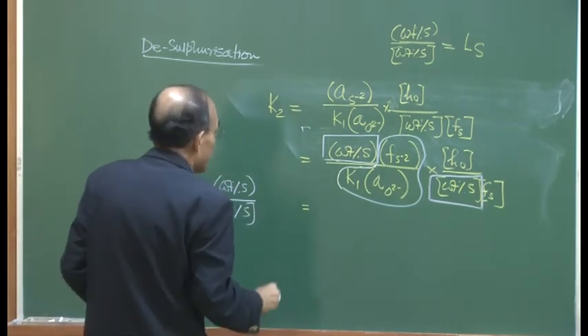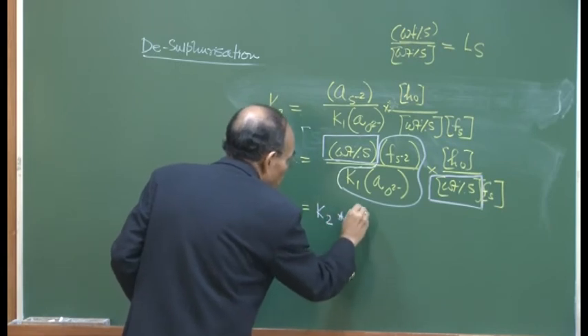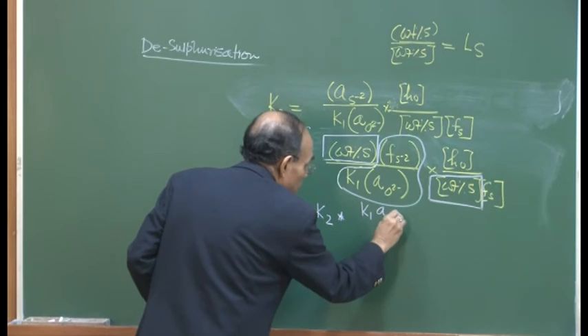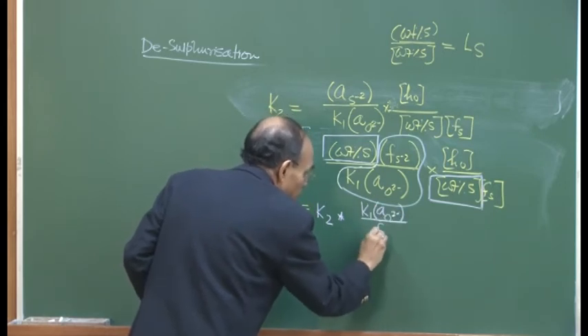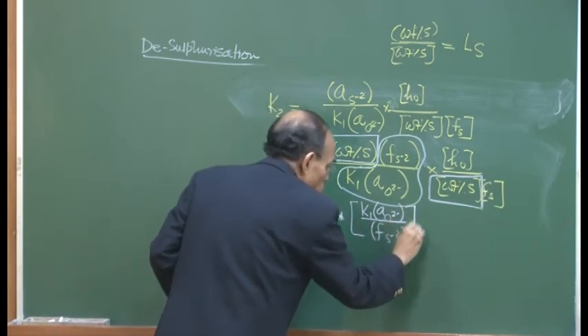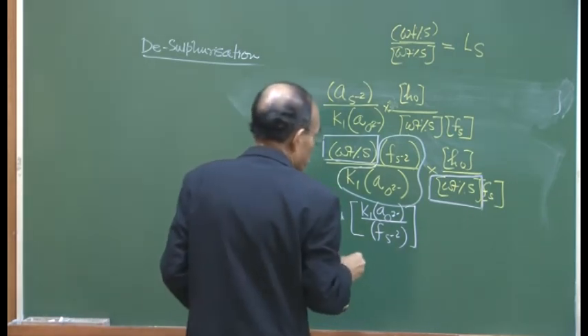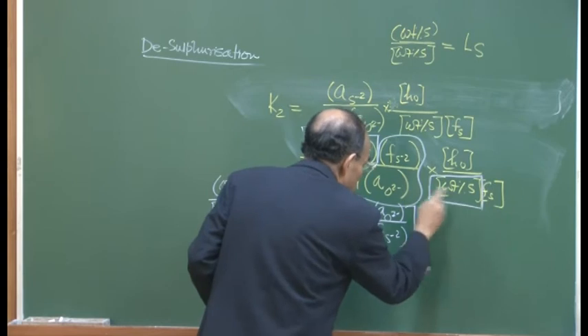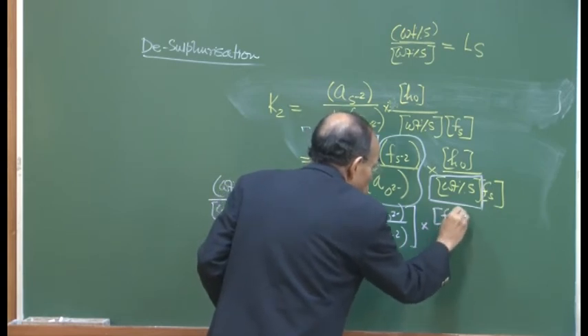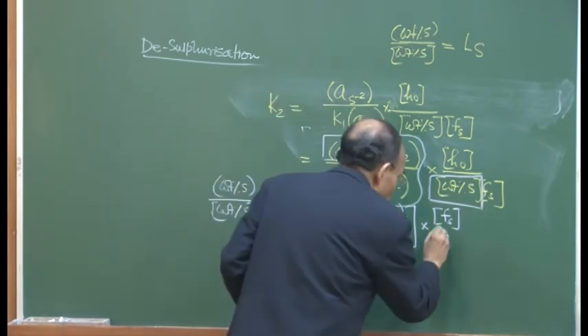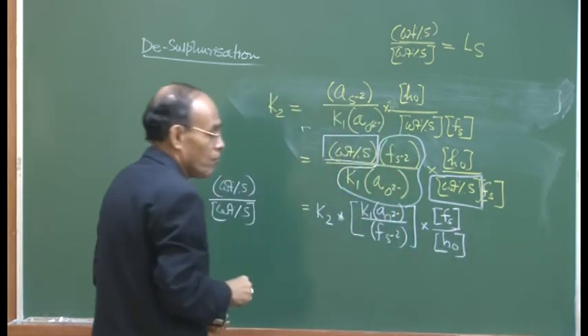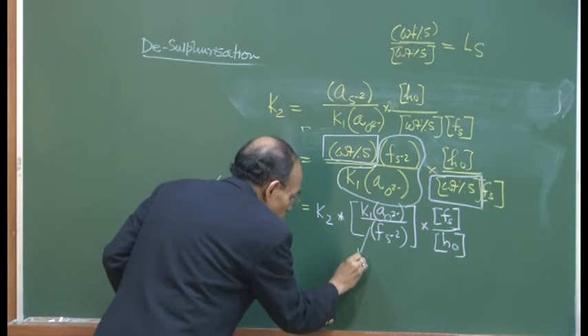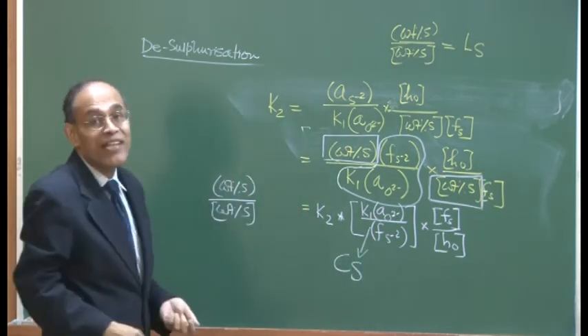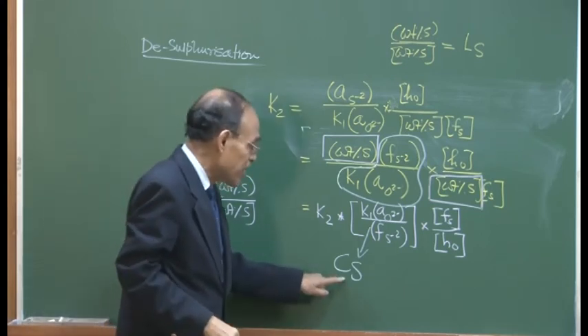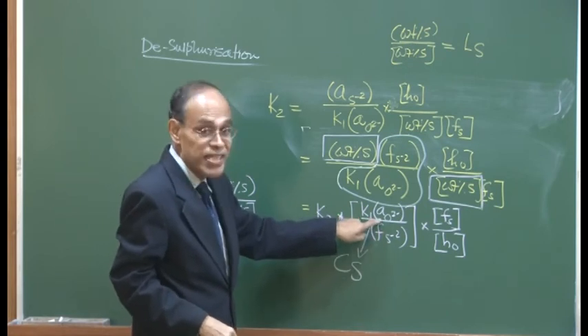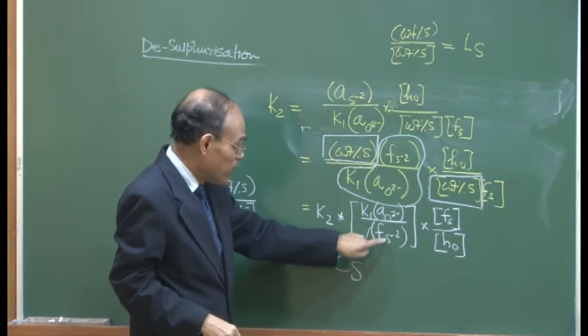And on the left hand side, we are going to get K2 into one parameter which is KaO2 minus divided by FS2 minus in the slag. And then we have FS will go up, and then we have HO will go down. In thermodynamic literature, this is given a special name, which is called the CS, the sulfide capacity of the slag, okay. And the sulfide capacity of the slag depends on the index of basicity, it is a function of the basicity of the slag, and it is a function of the activity coefficient in the slag.